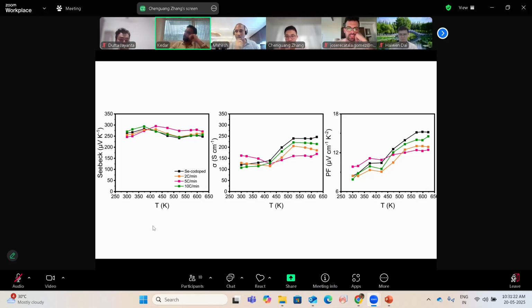What trend is not being followed? There's 2 degrees per minute, 5 degrees per minute. In terms of transport, I don't believe the trend; this is all error bar. So it doesn't really have a trend. If you talk about low temperature transport, I would believe trends, but I wouldn't say anything about trends at high temperature. So I would do low temperature itself.